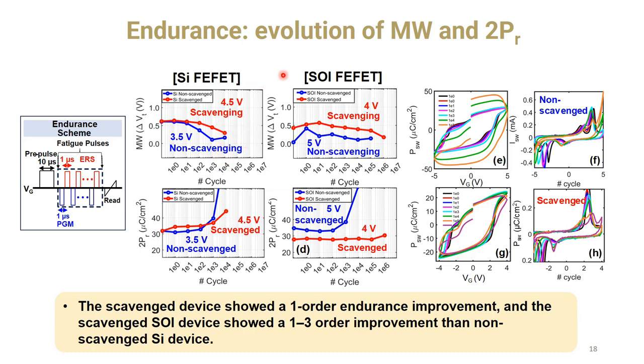However, there is a difference. The SOI FEFET has a benefit compared to the silicon FEFET. You can see the scavenged SOI FEFET has an endurance of 1E6, and the scavenged silicon FEFET has 1E4. So there is a two-order higher endurance benefit if we use the SOI FEFET. So the scavenging device has a one-order higher endurance benefit.